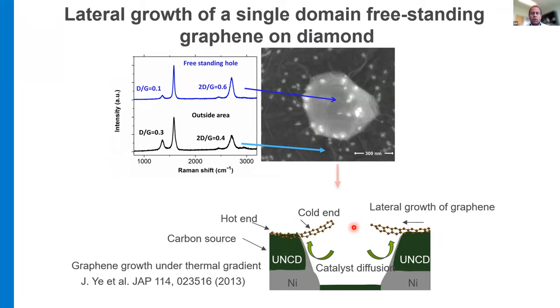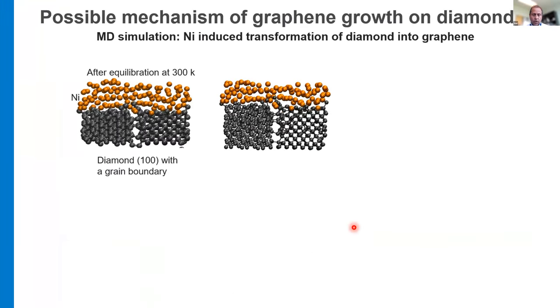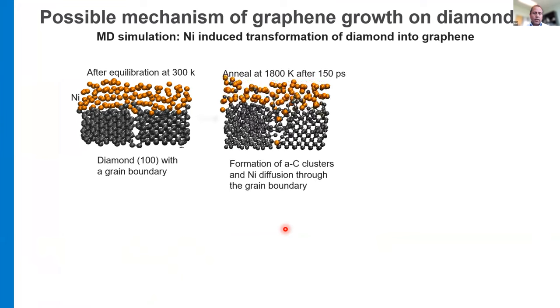Interestingly, we did not see the grain boundary, but intrigued by this process, we worked with our theory and modeling colleagues to understand this growth process even further. And so what we see is that as you put nickel on top, and as you increase the temperature, the grain boundaries, since the diamond is polycrystalline, it has a lot of grain boundaries.